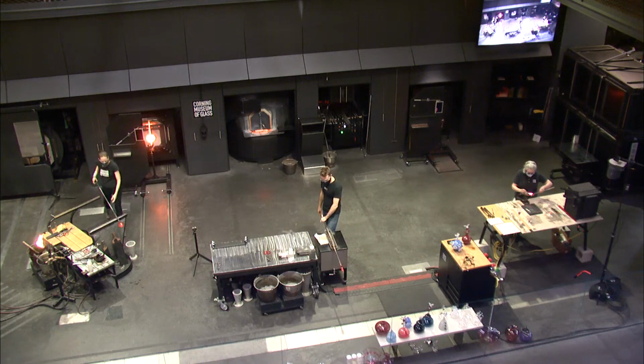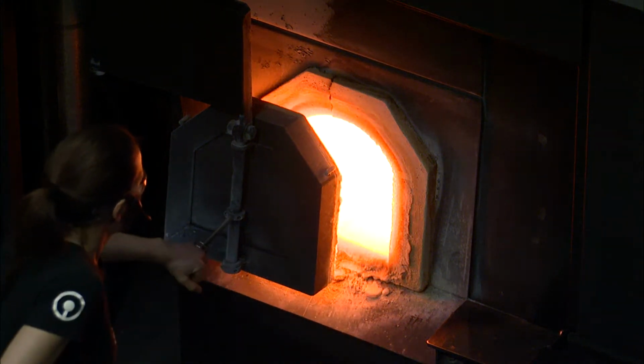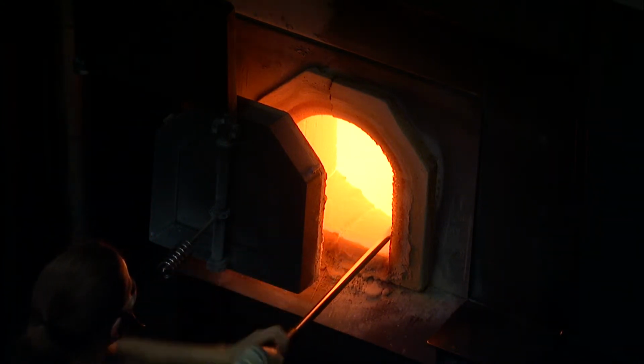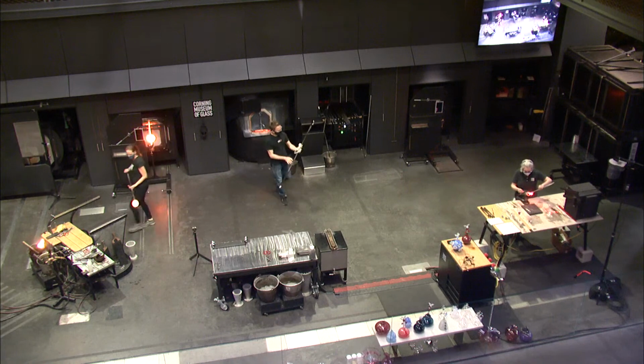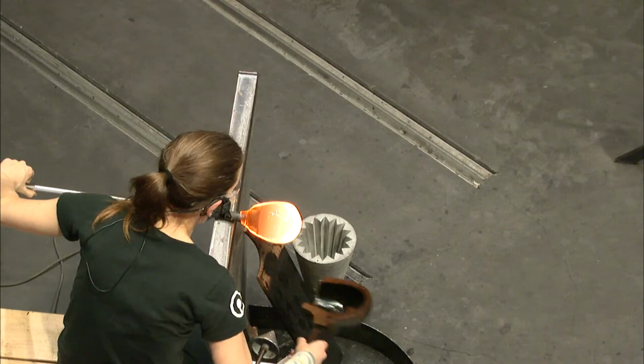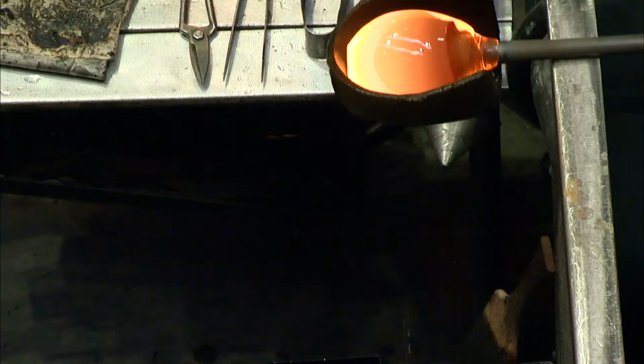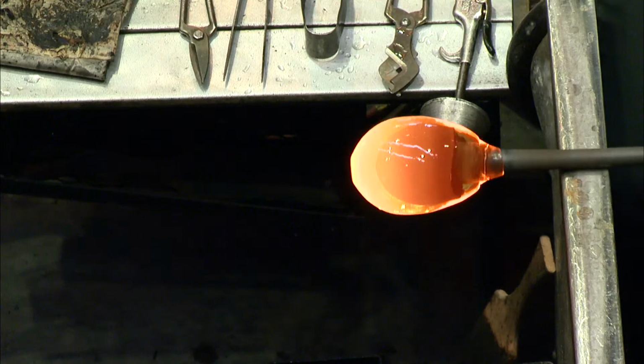So I'm just sort of picking away by adding one little bit and then another little bit, and I'm building up the glass for the shoes, but at this point not touching it down to the marble, because if I touch the glass down when it's not hot enough to flow, it can stick, but it won't. If it's not flowing together, it'll end up breaking apart later. It'll end up making a crack in the marble. So I'm very carefully not touching the marble with the colored glass yet. And then once I get enough glass in place for the shoes, I'll melt them a little bit more and then get them a little partially fused on there, and then stretch them to make the little points for the toes. It's really, really slow, and I kind of love that about it.